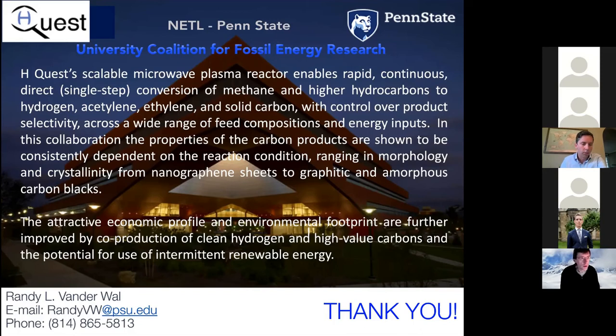But to your question, which is better, which is preferred, while the pure nanographene might be highly desirable, it's not clear that that's necessarily the most practical form of the product. Speaking somewhat more generally, the carbon black industry works often very closely with their customers, for example, for rubber, plastic, conductive applications, to tune the product characteristics for mixing, compounding, and all such characteristics. Having graphene as a fraction of something that resembles a carbon black in terms of processing and characteristics might be an easier inroad for that displacement, shall we say, rather than the complications of a new form with different mixing rheology characteristics.